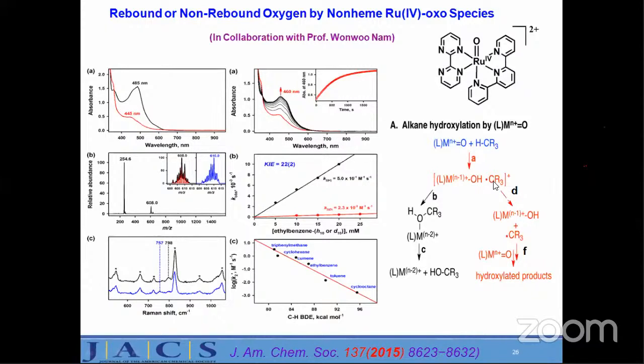In cytochrome P450 or in the case of heme systems, what is reported is that this species immediately rebounds back to the hydroxyl species, and then finally it gives the oxygenated product, going from +4 to +2 oxidation state. That is the product they give, and therefore the yields are quantitative. But recently, when many similar reactions were carried out with non-heme systems, the products were never close to 100%, like 80% or 90%. Unlike in porphyrin or heme systems, the yields were never that high. So what was the reason for that?